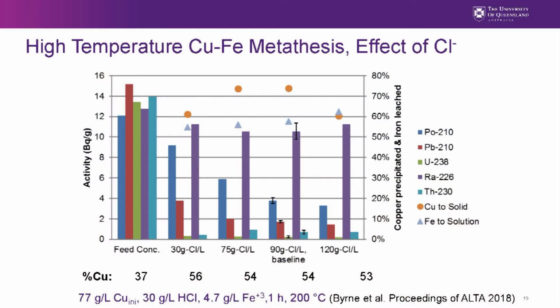On the left y-axis, we have the activity of the different radionuclides in becquerels per gram. And on the x-axis, we have the different solids. So this is the feed concentrate. This is the residue after metathesis exposed to 30 grams per liter chloride solution. The residue after metathesis exposed to 75 grams per liter, 90 grams per liter, and 120 grams per liter. So this is essentially the effect of chloride on separation of radionuclides during high temperature copper metathesis.